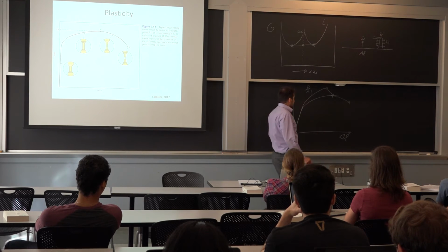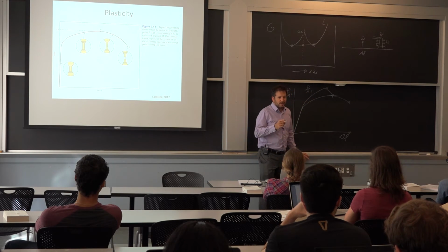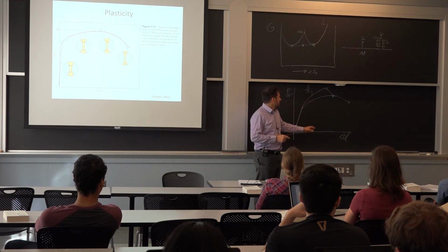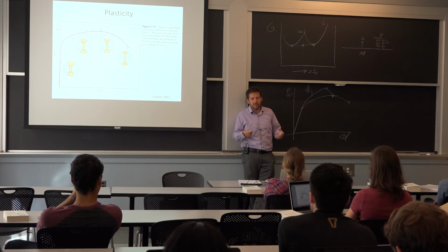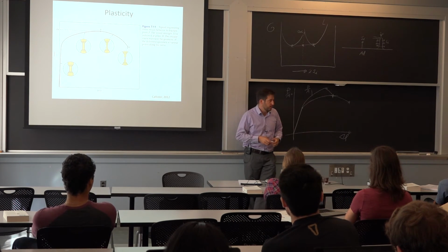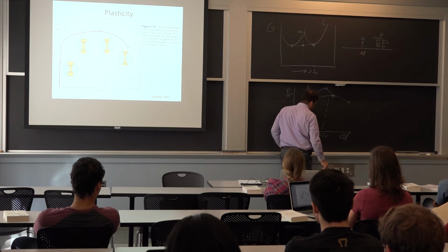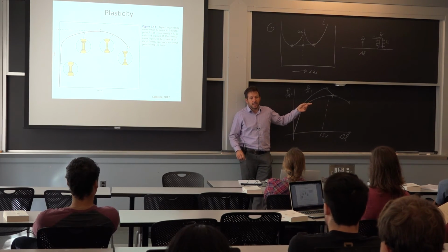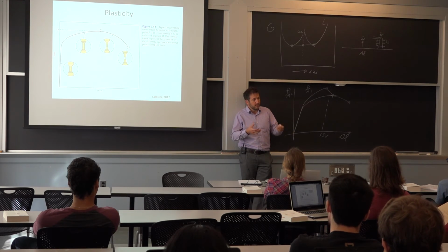And the main aspect in terms of deformation processing that I want you to keep in mind is that this keeps going up. Now, does it go up indefinitely? Not exactly. So at cold temperature, you can get perhaps 200% strain. So when you reach a deformation factor of about 2, you don't really have that much strain hardening anymore. But it's the type of number that we're looking at, as opposed to this here, which is typically just 15% strain. So there's a limited ability to collect the information beyond that. But if you did, you'll realize that there's more resistance always in the metal to deform.